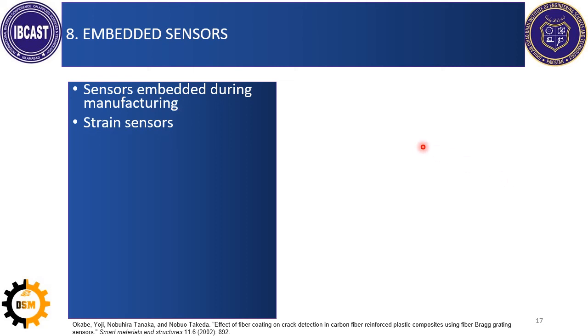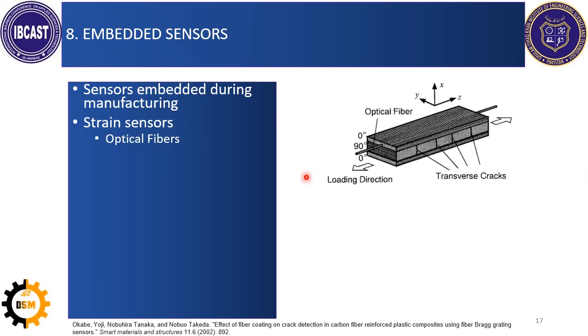Then we have the embedded sensors. So you make the sensor a part of the manufacturing process and they become a part of the structure. And typically they measure the strain. So these sensors inside the structure, which is preloaded, can, for example, be optical fibers. So you can see the transverse cracks are produced here, and optical fibers will sense that strain and give the data to the structural health monitoring.